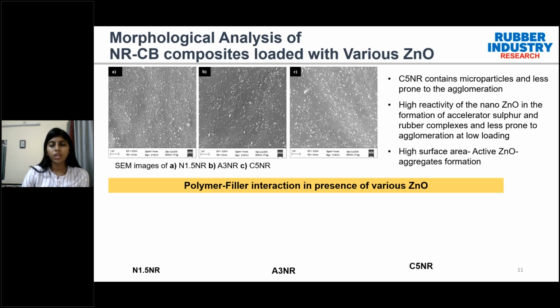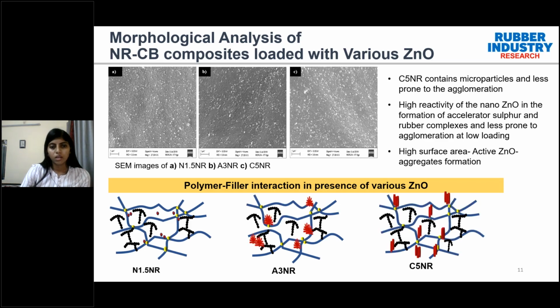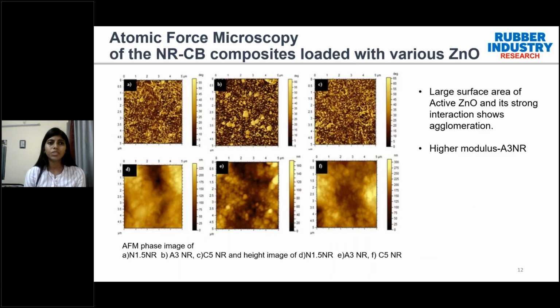Then when we look into the active zinc oxide at 3 pHr, due to the high surface area and the highly reactive sites of the active zinc oxide, it was prone to agglomeration or aggregate formation. So this is where the polymer filler interaction was obtained from the study for the nano zinc oxide, the active zinc oxide, and the conventional zinc oxide. Similar morphology was obtained for the atomic force microscopy also. For the active zinc oxide, there was an aggregate formation that leads to the higher modulus of the A3NR compound that we already discussed in the physical properties of the composites.